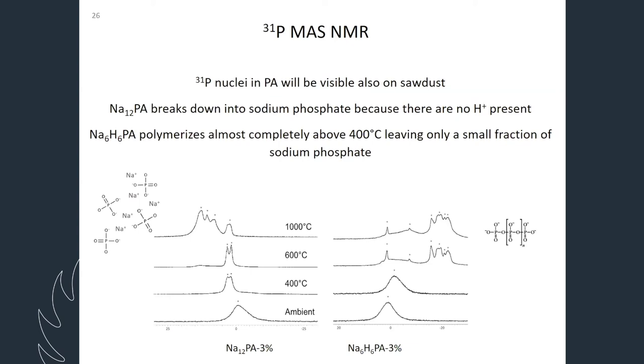Then we compared sodium, where we have replaced all of the 12 hydrogens in the phytic acid, and one version where we have replaced only 6 of them. And then we can see that the peaks shift in completely different directions when we increase the temperature. When we have 12 sodium, the peaks start to move to the left. And this tells us that we get the sodium phosphate. We don't get any polymerization at all in this case.